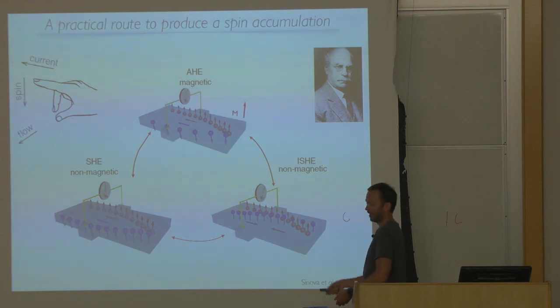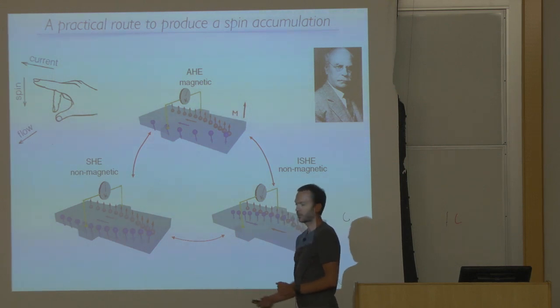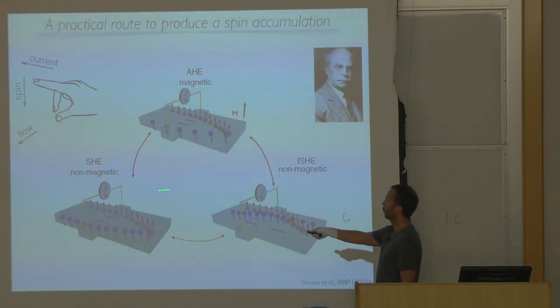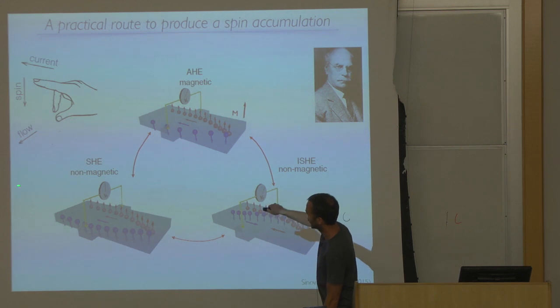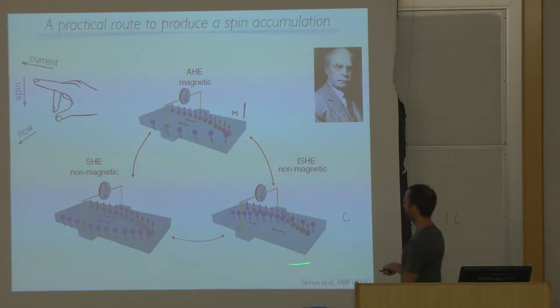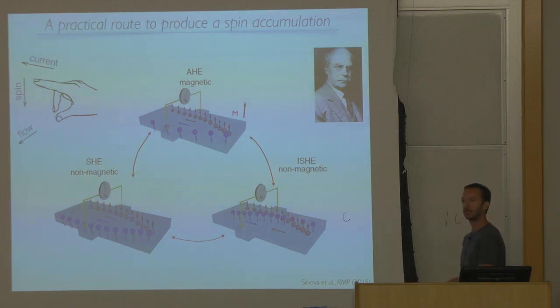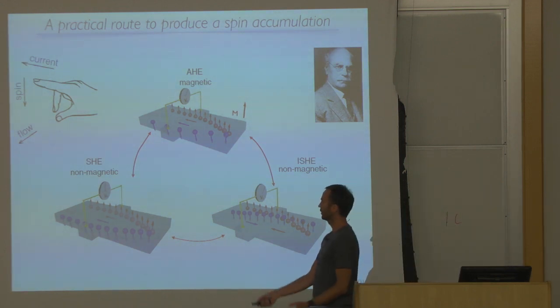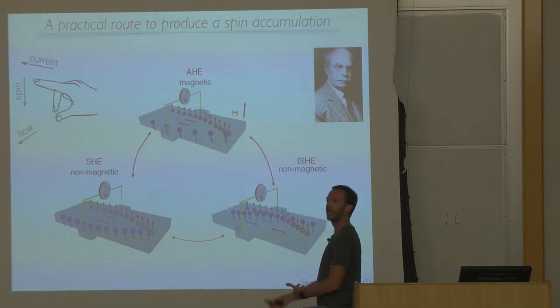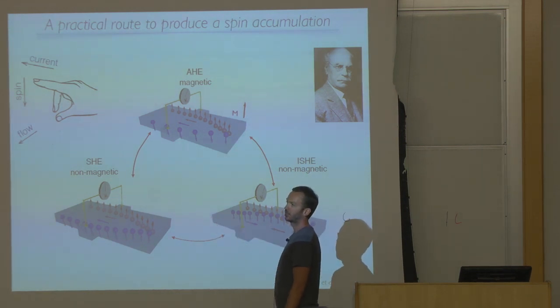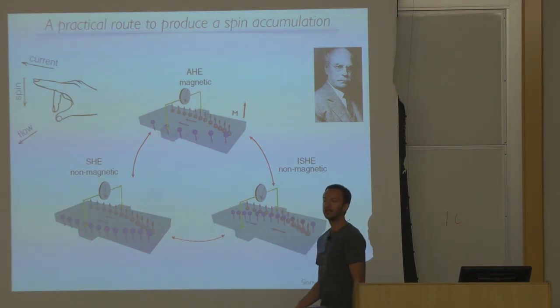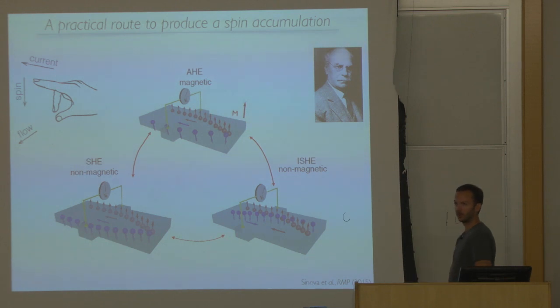And you could connect this edge now to your XY magnet and push spin into your XY magnet. So the spin Hall effect is the practical injection mechanism that couples electrical current to the spin dynamics. Okay, the reciprocal of that is the inverse spin Hall effect. So of course, we always have Onsager reciprocity. So if electrical current can inject spin, we can expect that we can detect this spin downstream by detecting electrical current through the inverse spin Hall effect.